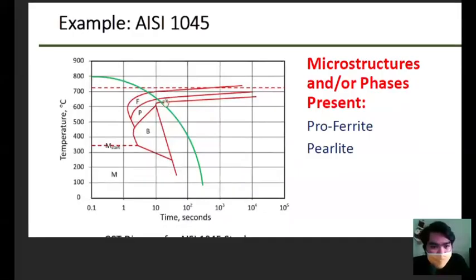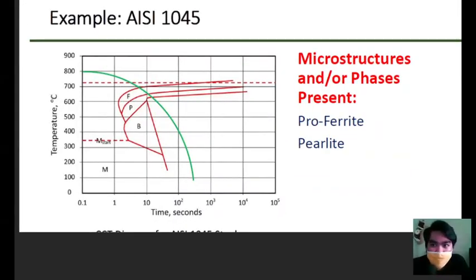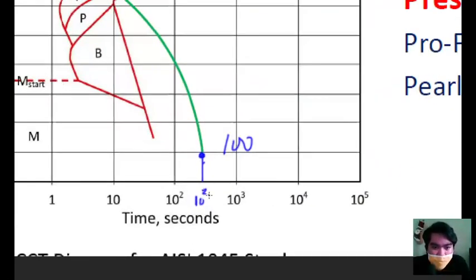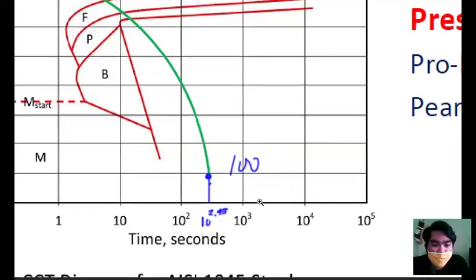So if you notice class, ito, we can estimate the cooling rate by just looking at the start and end points, no? So kunwari ito, we started at 800 degrees Celsius. Tapos nag-drop tayo to 100 in around 10 to the, and I discussed this sa podcast din, paano natin ma-estimate yung logarithmic scale. Yung exponents natin is naka-linear, no. So dito sa exponential scale, ang naka-linear yung markings niya is actually the exponents. So dito, this is somewhere around 2 point, I'm estimating class, no? This is somewhere before 2.5. So ang estimate ko, this is supposed to be mga 2.45. Yun yung estimate ko class, no? So this is 10 to the 2.45.